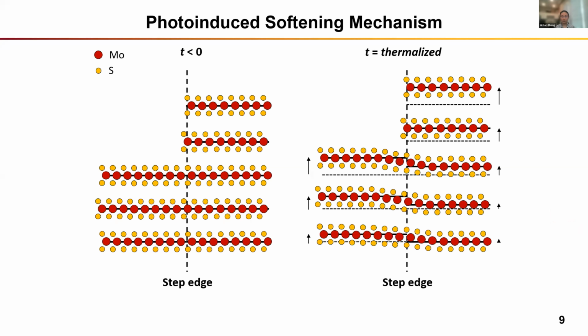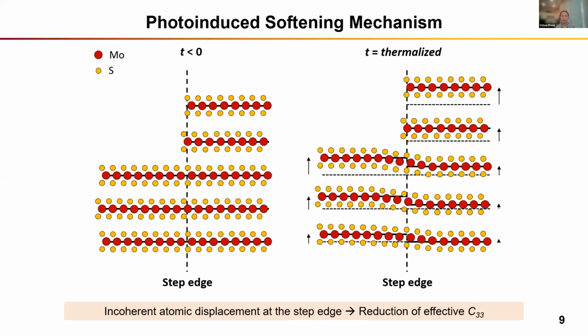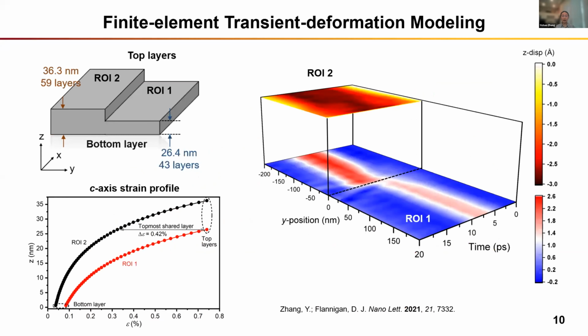However, each layer must be continuous. So the z-axis atomic movement is much less coherent at the step edge as compared to the bulk region far away from the step edge. So this incoherent oscillation directly leads to this reduction of the effective C33 elastic constant, and then subsequently the phonon softening that we observed experimentally. I then did some finite element modeling to verify the hypothesis. So the photoexcitation was simulated by applying an impulse of a z-axis strain as shown here.